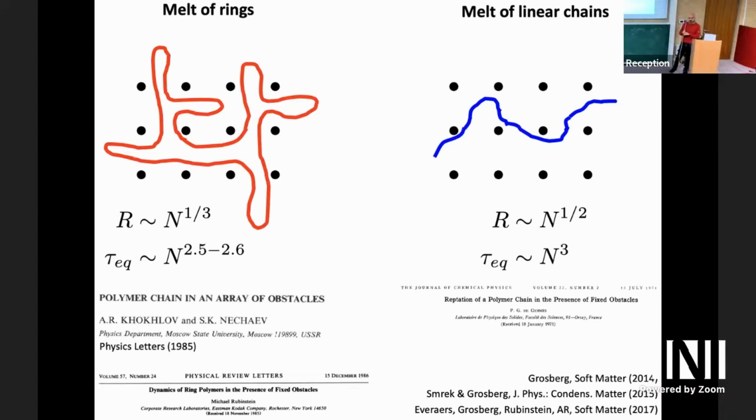The question is the mesh size. Yes, and the mesh size is much larger? In this case, no, not at all. It's about 4 times the persistence length. If you do the calculation and the proper mapping, we saw that this is in the realm of loosely entangled polymer. So the entanglement length for this object is roughly about 4 times the Kuhn segment. It's a bit larger, but compatible. It's not 20 times. And this is also because, if you do the calculation, these polymers are in a semi-dilute solution, so it's not really a proper melt. So we're talking also about above the entanglement length of the solution. Okay, thanks for the question. It's quite important.